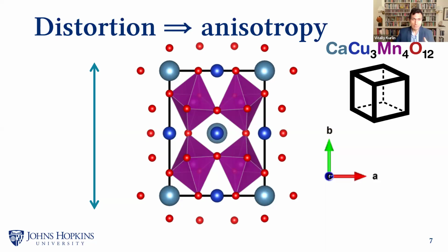And similarly, of course, the periodic translations under the new basis 2A, B, and C, right? Then after this perturbation, this doubled cell becomes primitive, so minimal by volume, right? So it changes now dramatically, although the material itself is almost the same. Yes. In that case, if the unit cell itself, what we have defined as this imaginary box, has changed dramatically, the CDM value will change dramatically. And it's definitely an open question when we're talking about supercells or some kind of perturbation that now means you can no longer reduce the cell, or that you can now reduce the cell. How to handle those specific situations is something that we're still looking at.